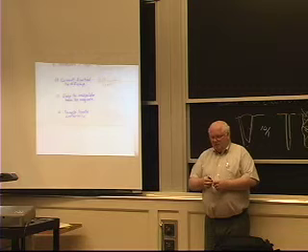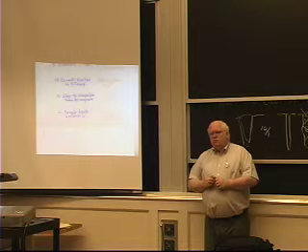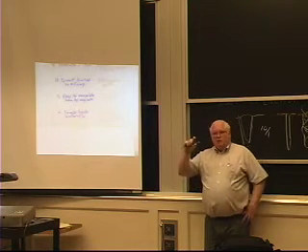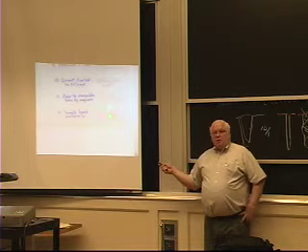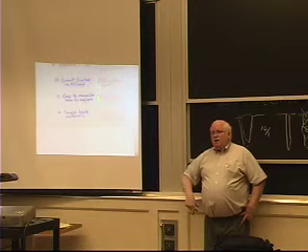The Naval Research Laboratory was kind of the center for this in the 1970s. They had one of the first 25 kilowatt lasers. It's about the size of this room. But for research, they were welding 1/2 inch and 3/4 inch thick steel, and on HY80 they actually got better properties in the weld metal for an autogenous weld, because when they went in there, they found that they had preferentially vaporized away the inclusions.